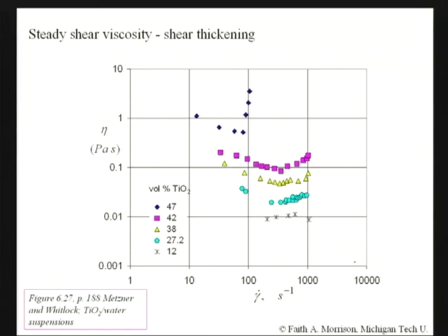Look at what shear thickening looks like. Shear thickening looks like, well, actually it's shear thinned for a very small, maybe third of a decade, and then it's shear thickened. This is our most pronounced shear thickener, but it also shear thinned, and then it's shear thickened by 3/4 of a decade. So shear thickening is a much less often seen event, and again, a much more subtle effect than shear thinning. It's not too common, and it's due to structured interactions between these particles, the titanium dioxide particles. I'm not even going to include shear thickening on our summary.